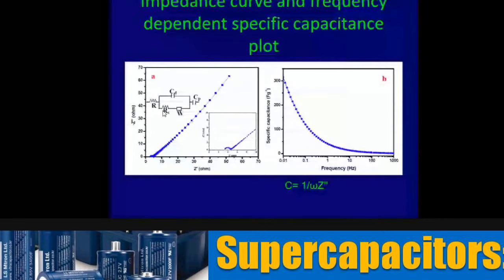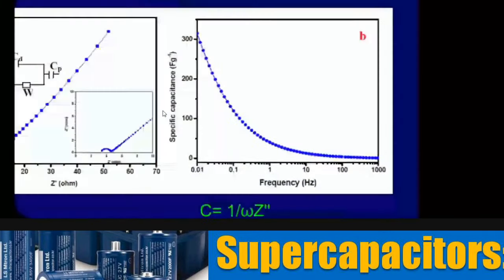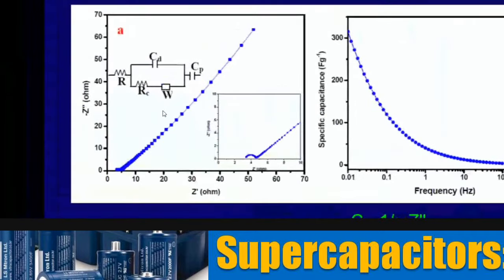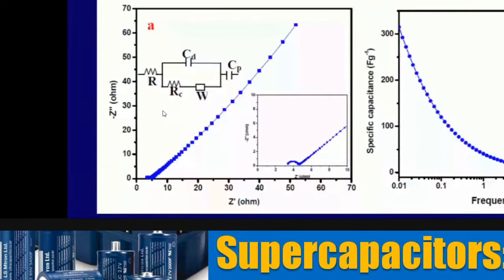The next important thing is the electrochemical impedance spectroscopy. Now you can see that this slide has got an equivalent circuit. R is the series resistance. Then we have a charge transfer resistance, a Warburg resistance, a double layer capacitance, and the capacitance.